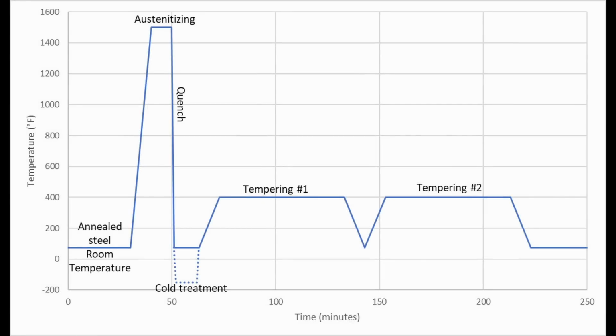Tempering has similarities to austenitizing in that we are heating the steel to some temperature and then holding it there. The main difference is that tempering is from a much lower temperature, such as 300 to 1050 Fahrenheit, which would be 150 to 565 Celsius. This means it can be performed in less specialized equipment, and less protection from the atmosphere is required because not as much oxidation happens at the low temperature. Though many custom knife makers will use a kitchen oven or a toaster oven, that can lead to more variability than a tightly controlled furnace.